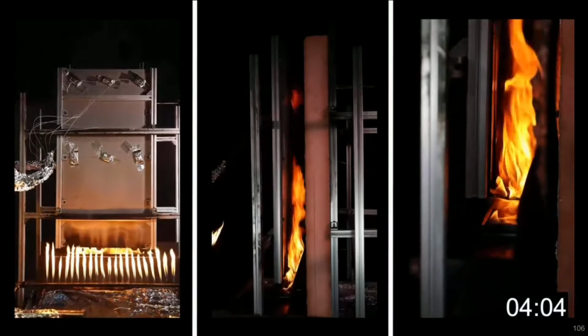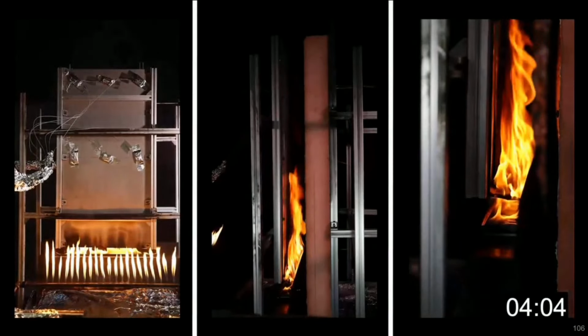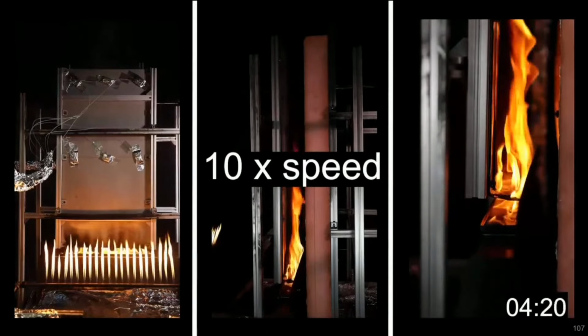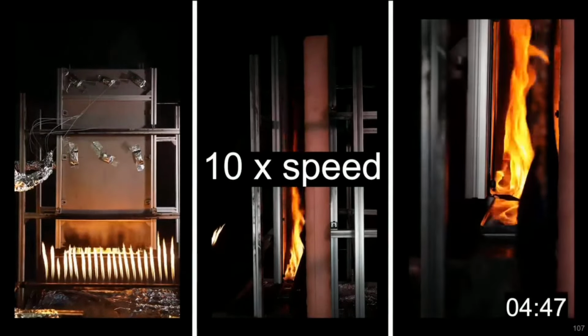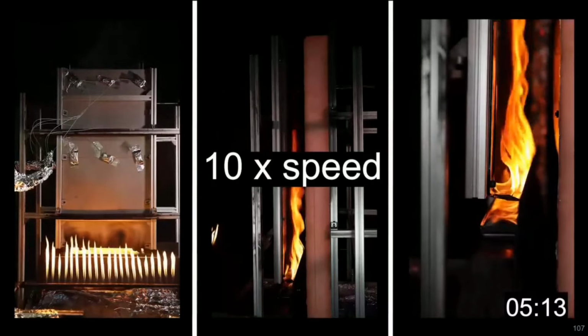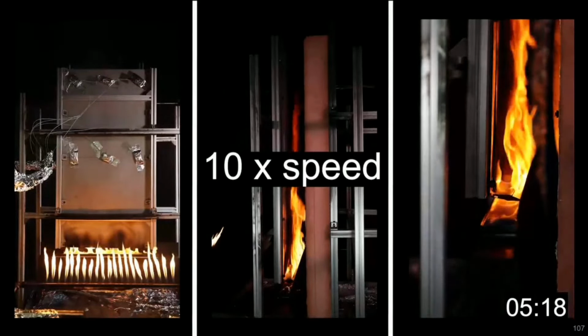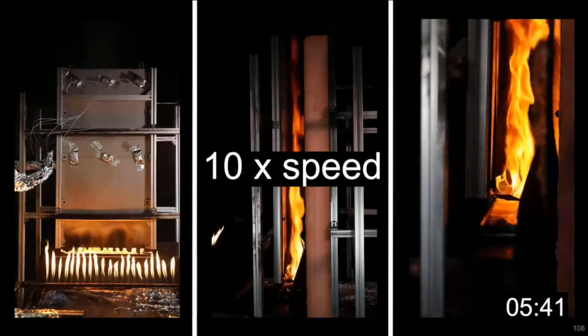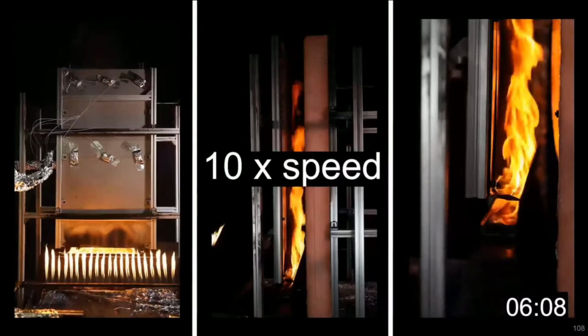And after 4 minutes, the flame height within the cavity continues to increase gradually as more molten PE mobilizes and exits the ACM panel. At about 5 minutes and 19 seconds, we'll see that the flames become visible above the experimental apparatus, and you'll see this particularly in the leftmost view. And you remember now that the line burner has been removed, so this is just burning polyethylene. So you can see in the leftmost view, flames above the rig.